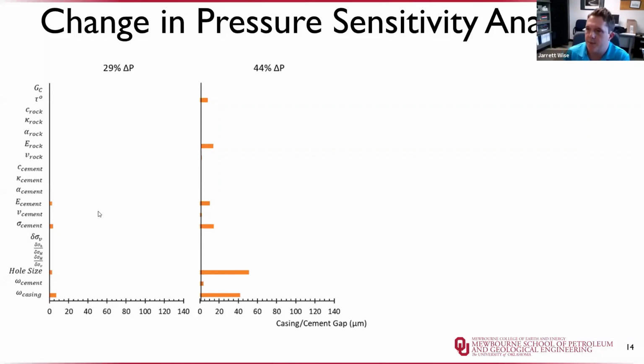So if we continue to reduce the pressure up to 44%, we see that our microannuli are starting to get bigger in magnitude with the same parameters as before, but now we're starting to add in a few more, like the Young's modulus of the rock and the tensile bond strength. But we really see that the hole size and casing thickness are the main ones, where they take it from like 1 micron all the way up to about 40 to 50 microns in size. So pretty significant change.